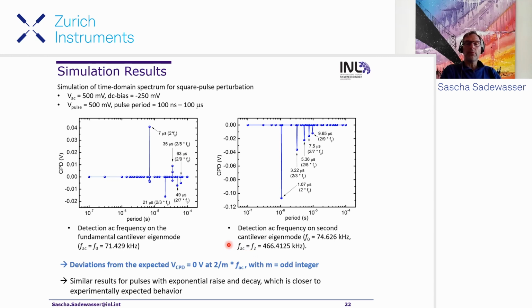And this can be reproduced also using an AC voltage at the second resonance, which is what we do experimentally. And we see again the same. So it's not related to the cantilever fundamental resonance, but it's actually related to the AC frequency. And this artifact happens at 2 over M times the AC frequency, where M is an odd integer.